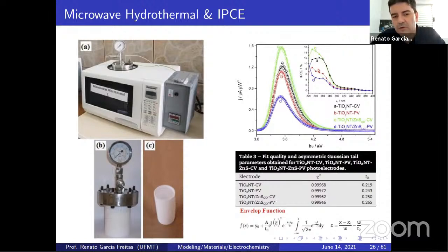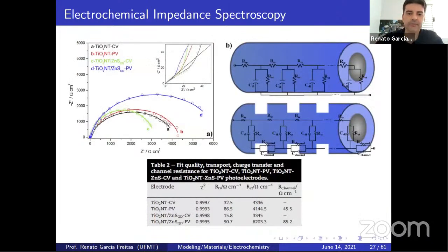So we observe not only the increase of photocurrent efficiency for quantum dots, but we observe as well the efficiency of the envelope function to fit these values. And a proper system for a proper model, isn't it? Because we have a nanotube like the one with a constant voltage, with a pictorial representation like the one, a two-channel transmission line model, and this one for pulsed voltage. So we have the transport resistance, the double layer capacitance, charge transfer resistance, and accumulation of charge on these parts here to fit the resistance. We call it the channel resistance and the channel capacitance.